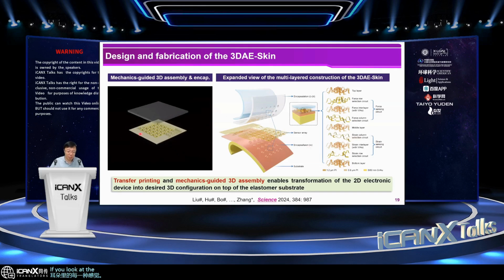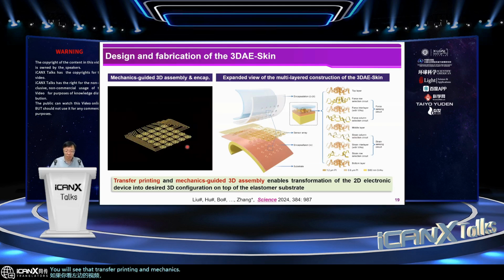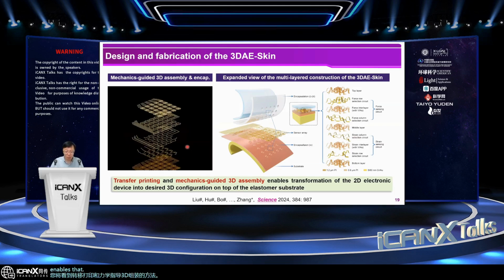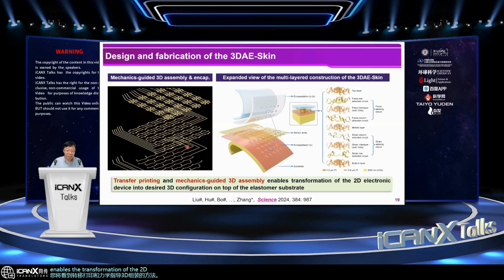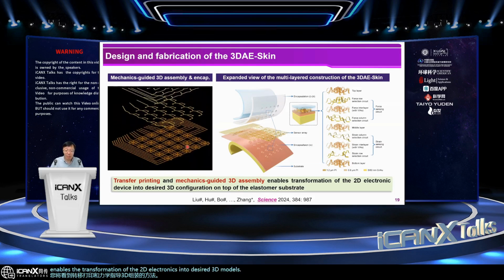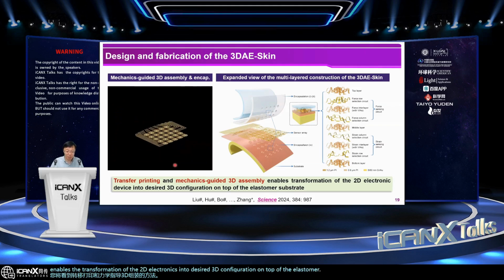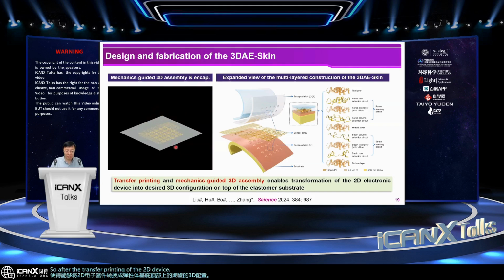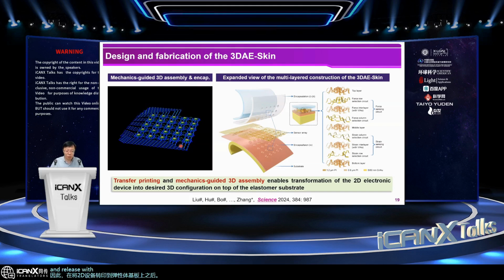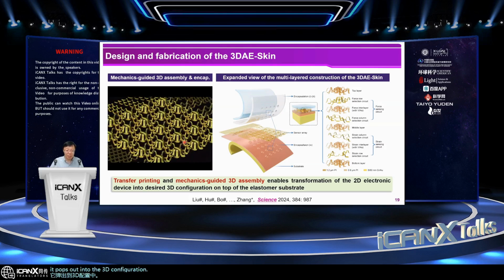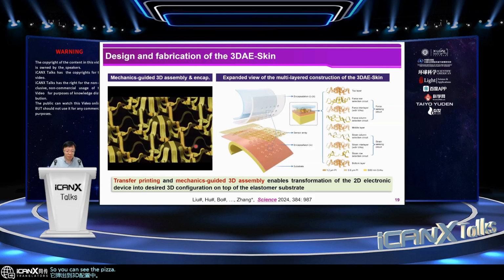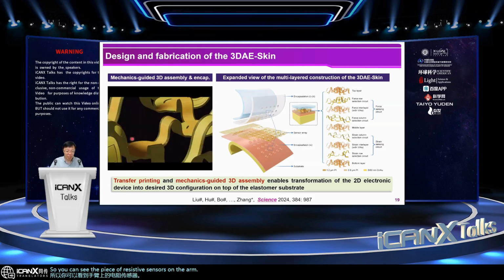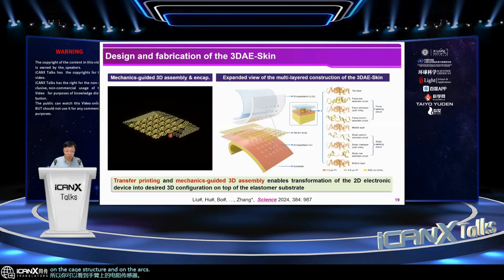If you look at the video on the left, you will see that transfer printing and the mechanics guided 3D assembly approach enables the transformation of the 2D electronics into designed 3D configuration on top of the elastomer substrate. So after transfer printing of the 2D device onto the elastomer substrate and release the pre-strain, it pops out into the 3D configuration. So you can see the piezo-resistive sensors on the cage structure and on the arc structure.